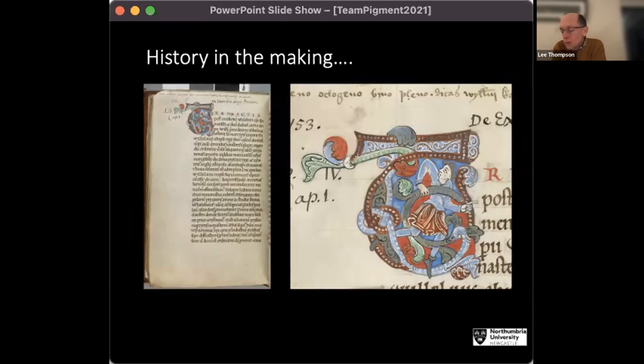So you mentioned your multispectral imaging, and you talked about actually imaging in narrow wavelength bands. So how narrow are those bands typically? 10 nanometers full width half max on the bands, and it's in 50 nanometer increments from 400 nanometers up to about 850. And then we've got two edge passes for the UV and the near infrared.